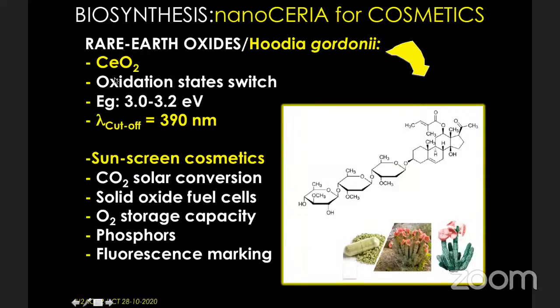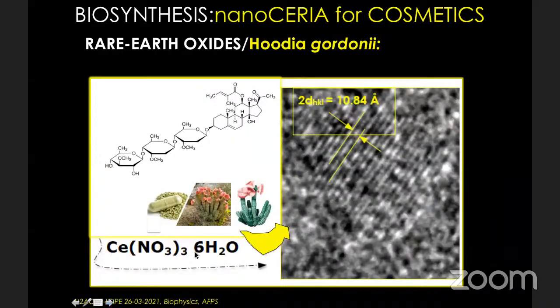We are interested in cerium oxide because we want to show that it is an ideal material for nanocosmetics. We were targeting it because it has a band gap as close as TiO2, as well as ZnO, but with the advantage that in terms of ROS, reactive oxygen species, it is low relative to the others, so it's not toxic to the skin. It is also used extensively for CO2 solar conversion, for SOFCs, for oxygen storage capacity, as phosphor, and as fluorescent marking. Well, combining cerium nitrate with the natural extract of this Hoodia gordonii powder containing these P57 compounds, which is able to give birth to aldehydes, we can synthesize.